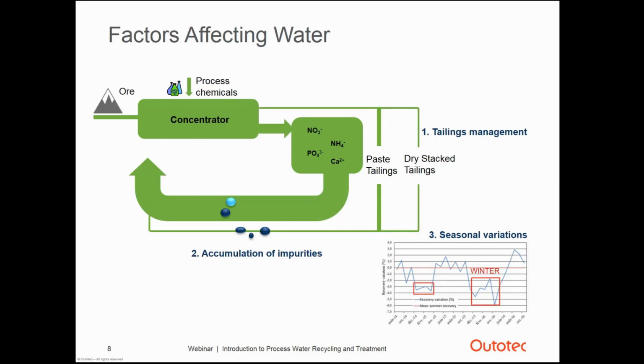in a processing plant. Then when we start to recycle more water and turn more towards paste or even dry stack tailings, the retention times get shorter. It's typically around 4 to 8 hours. The reactions that were possible in the conventional tailings dam don't have time to take place, and impurities can start to accumulate in recycled process water.